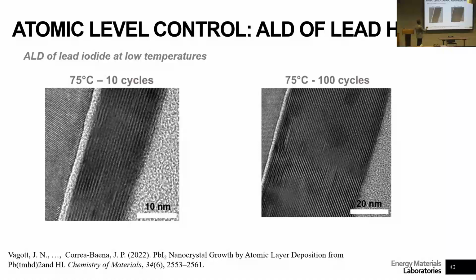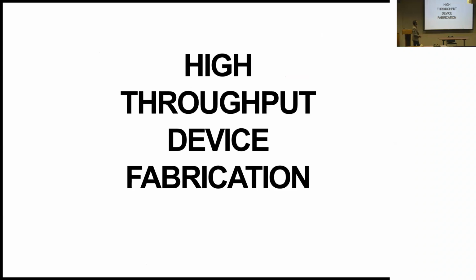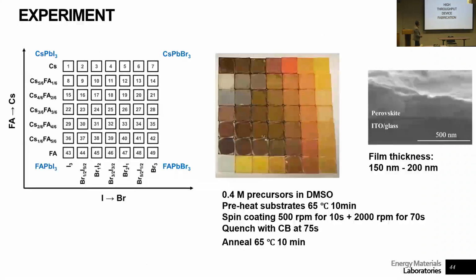Here's 100 cycles, which actually we got about 70 layers in there, which is more close to what we want. All right, so high throughput device fabrication is something else that we do, and I'll go over this pretty briefly, but we do a lot of compositional mixing to try to understand how properties change. And so you can immediately see here, different band gaps, yellow, red in the middle, and dark. And so band gaps are shifting, so that's good. That's a tunability that we want.